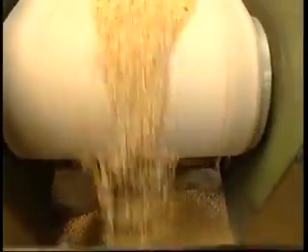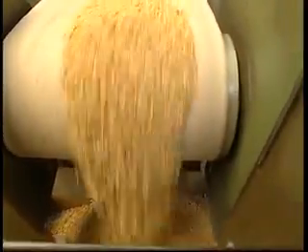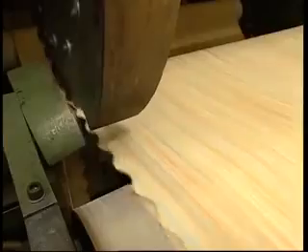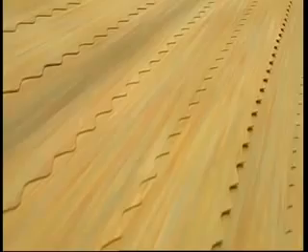Once the basic material is ready, manufacturing can begin. Jute, again a natural product, serves as the base for the linoleum. The 3,000-meter roll slowly progresses towards the calender rolling mill. The linoleum granulate falls down before the first rolling mill. The high pressure of the rolling mills, which rotate at different speeds, create a linoleum sheet with a colorful striped pattern. The wavy edge ensures the linoleum is evenly spread.